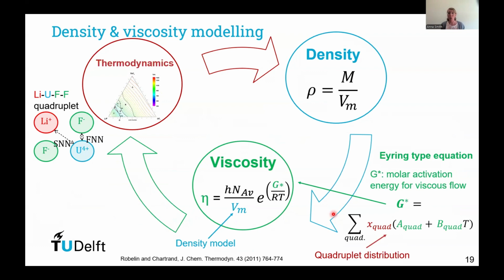Once we have done that, we can go one step further to develop a viscosity model where we have a target function for viscosity that is expressed with a Eyring type of equation, this one, related to Planck constant, the Avogadro number, as well as the molar volume. So here is again a link with the density model and the thermodynamic model. And then we have this exponential term with this G star, which is the molar activation energy for viscous flow, expressed as a function of the quadruplet distribution and some terms that are optimized in the model. So here again, you see that really we have a viscosity model that still is very much related to the thermodynamic description and to the description of density.